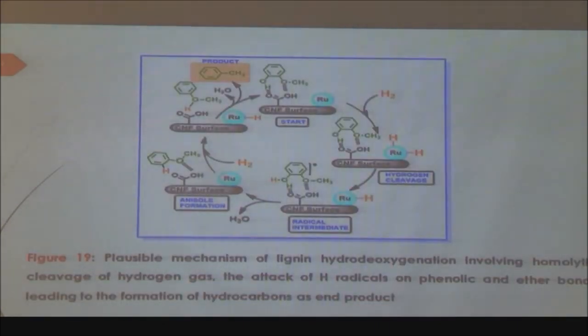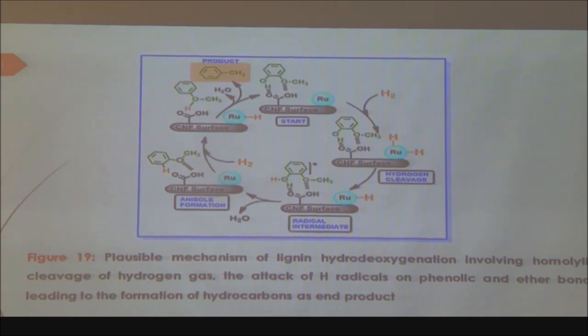Then, based on this, we tried to see how the solvent will interact, and what the activation energy barrier is for different molecules. We started with the molecule guaiacol, and we found that it adsorbs onto the carboxylic group, and when it is present nearest to the metal center, it cleaves the hydrogen as usual. This hydrogen, when cleaved, prefers to go in the radical form, because we studied both: if it is heterolytically cleaved, what is the activation energy, and when it is homolytically cleaved, what is the activation energy. And the computer says that when it is homolytically cleaved, the activation energy is less. So we propose that the radical pathway is preferred the most. But if the radical pathway is blocked, it will be forced to go for heterolytic cleavage.